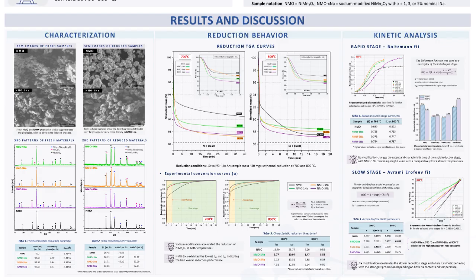A more noticeable difference appears after hydrogen reduction. Pristine NMO is mainly transformed into metallic nickel and cubic manganese oxide. In contrast, the sodium-modified materials additionally show the formation of tetragonal manganese oxide. Therefore, sodium modification is associated not only with changes in reduction kinetics but also with a different phase evolution during the reduction process.